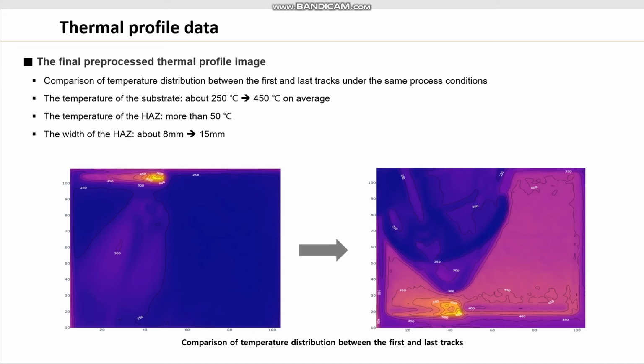Also, it can be seen that the size of the heat affected zone increased due to the accumulated heat from the previous bead. The temperature of the heat affected zone increased by more than 50 Celsius degrees, and the width of the heat affected zone increased about twice, from about 8 mm to 15 mm.